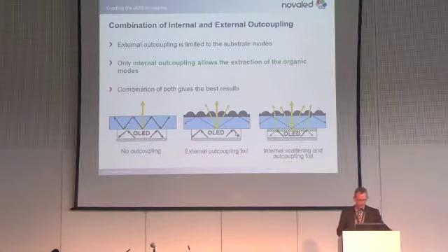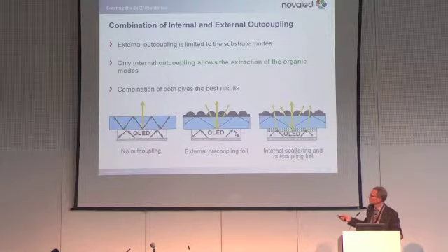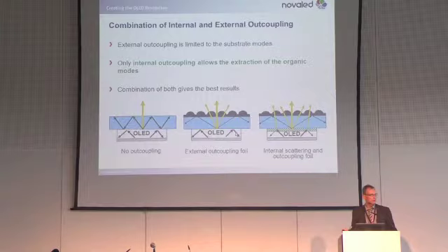So this outcoupling is shown on the next slide. How do we achieve this, let's say, 40% outcoupling or 45% outcoupling? The left picture here is a normal OLED, the standard OLED with 20-25% outcoupling. The light is created inside the organic LED with a refractive index of 1.7, and it's partially trapped here. A part of the light is transferred into the substrate, which has 1.5, it's glass, let's assume, and also is trapped here, and just this tiny little amount of light goes out.